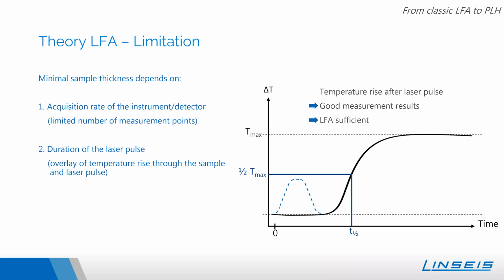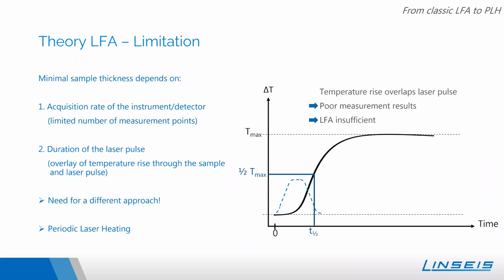As you see on the right side, a good measurement is displayed. The temperature rise is after the pulse. The LFA is sufficient, and you gain a good measurement result. But what happens if the situation changes and the temperature rise of the sample is too fast and overlaps with the laser pulse? Then it would result in poor measurement results, and the LFA wouldn't be enough for your application. But here at Linseis, we are now offering a different approach to surpass this limitation, and we call it periodic laser heating.